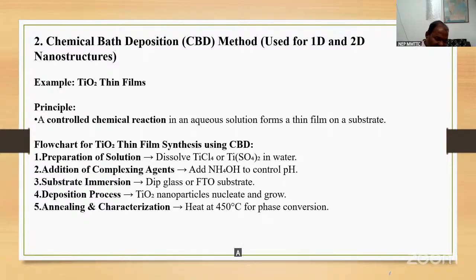A controlled chemical reaction. Now the TiO2 thin film synthesis using CBD, chemical bath deposition. Thin films, meaning two-dimensional materials or films, can be tailored or engineered. Preparation of solution: dissolve the titanium tetrachloride or titanium disulfate in water. We have to dissolve the titanium tetrachloride or titanium disulfate in water.